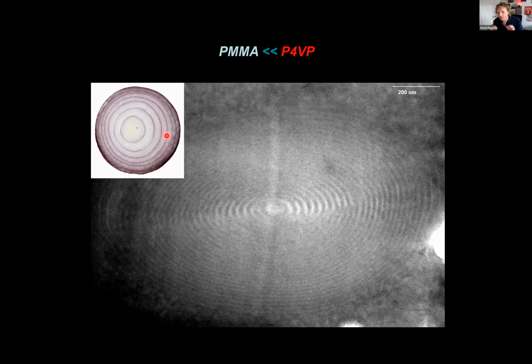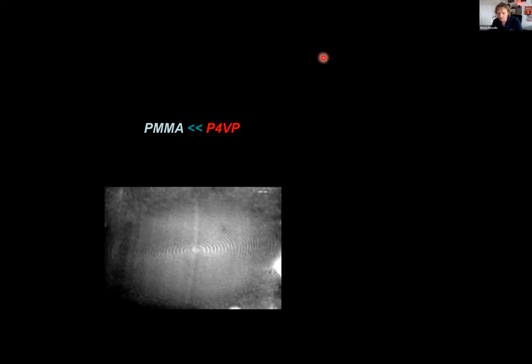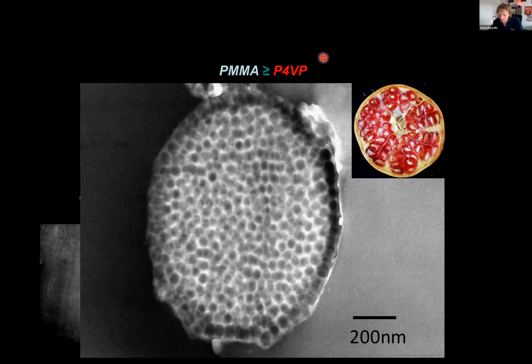And then if we changed the length of the two different blocks, we should be able to change the structure. So we were working with methyl methacrylate and vinyl pyridine, and we changed the lengths. And when we changed the lengths, we changed the structure. And we saw this. This time, instead of lamella, we saw these spherical areas where we had zones of polyvinyl pyridine inside a sea of PMMA. And we decided this looked a bit more like a pomegranate.